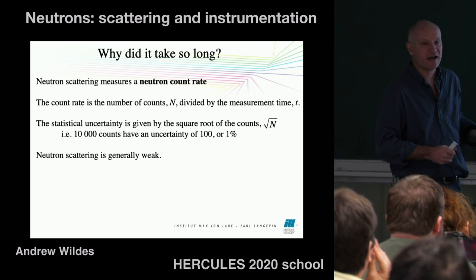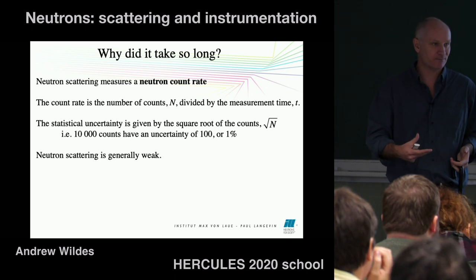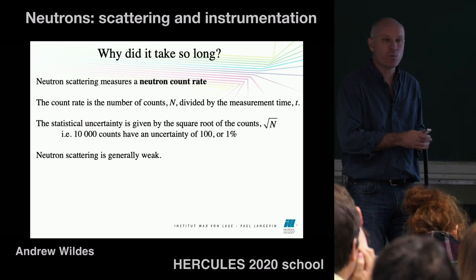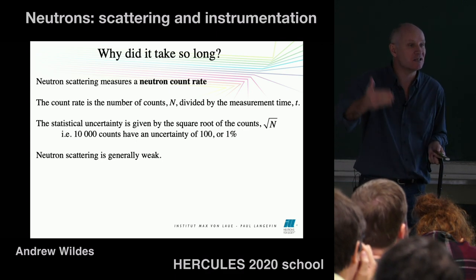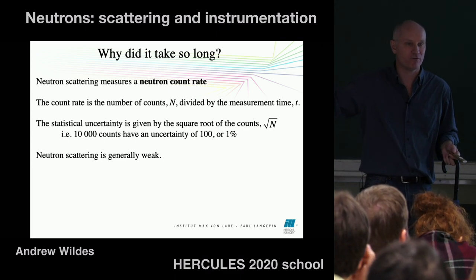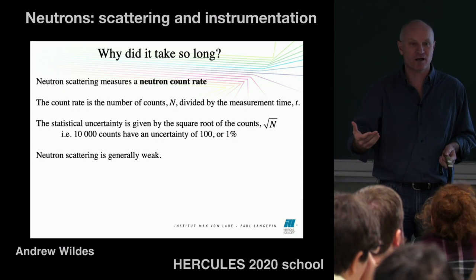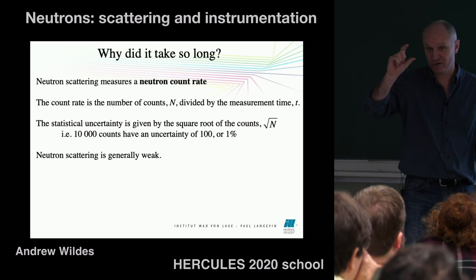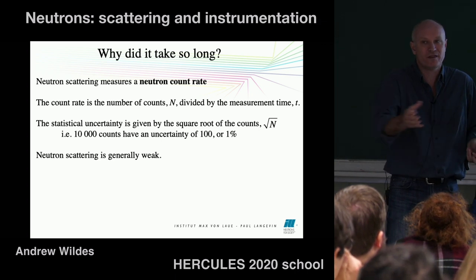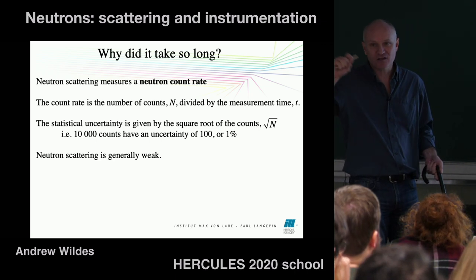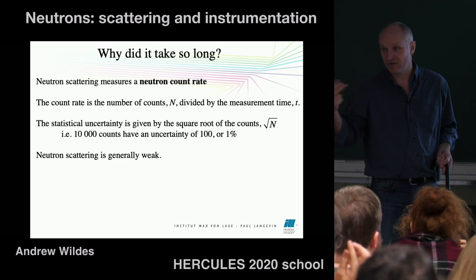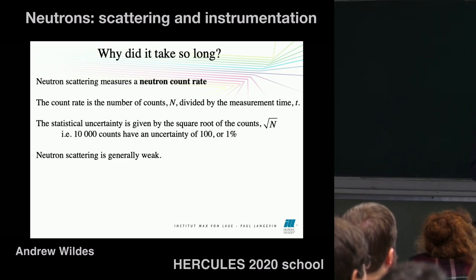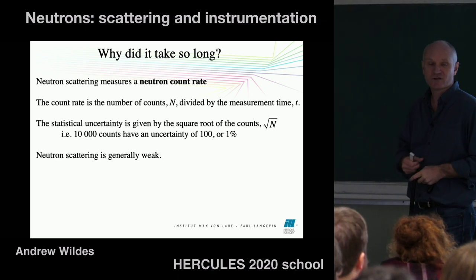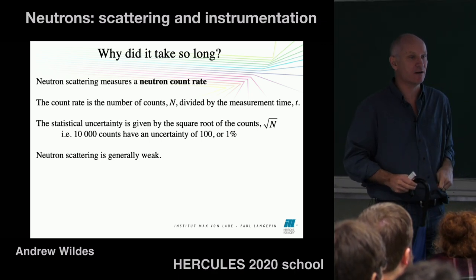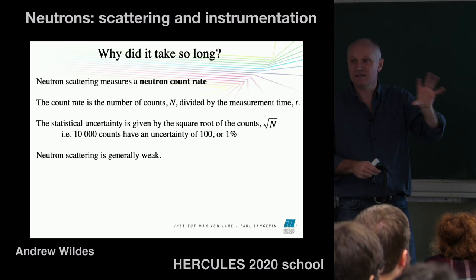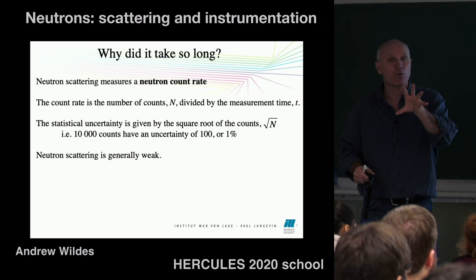All right, so neutron scattering, what you're trying to measure is a count rate, number of neutrons per second. And now you have to worry about the accuracy of your measurement. It's a statistical process. You count a certain number of objects, and after a certain period of time, you can say with a certain precision or a certain uncertainty whether or not it's a real thing or whether it's just an artifact of something else. And that uncertainty, according to the statistics of the way the measurement's carried out, is given by the square root of these number of counts. So to give you an idea, if you measure 10,000 of these counts, whatever they are, the uncertainty statistically is 100, or about 1%.